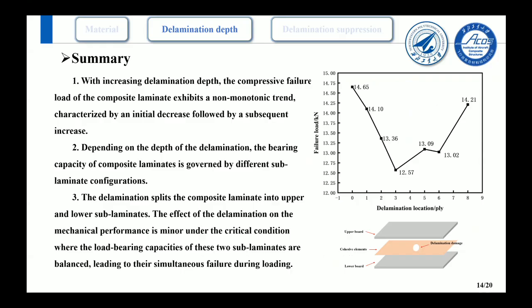In summary, the key findings from the above analysis are as follows. To begin with, the compressive failure load of the composite laminates exhibits a non-monotonic trend with increasing delamination depth, characterized by an initial decrease followed by a subsequent increase. In addition, depending on the depth of the delamination, the bearing capacity of composite laminates is governed by different sublaminate configurations. Finally, the delamination splits the composite laminate into upper and lower sublaminates. The effect of the delamination on the mechanical performance is minor under the critical condition where the load-bearing capacities of these two sublaminates are balanced, leading to their simultaneous failure.